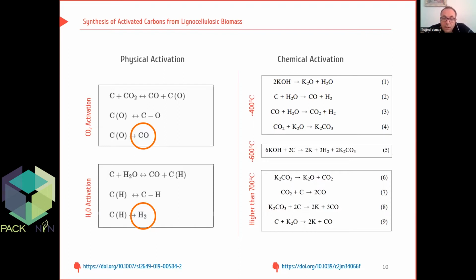In carbon dioxide activation, carbon and oxygen complexes are created in the first phase, and they are so stable. Some of the complexes can decompose into carbon monoxide, leaving a free carbon surface for an additional reaction.